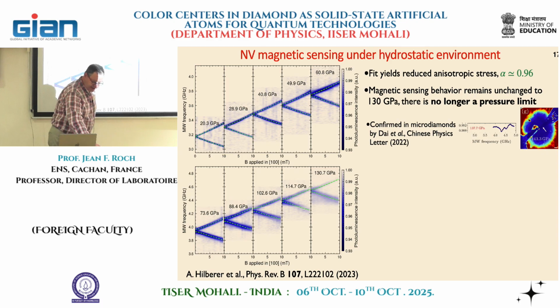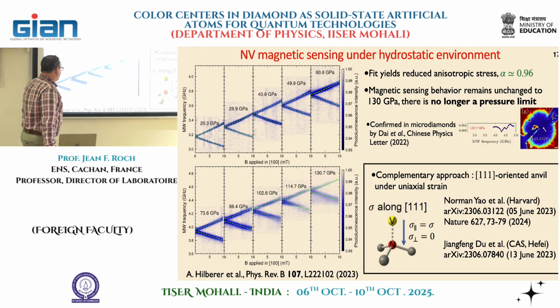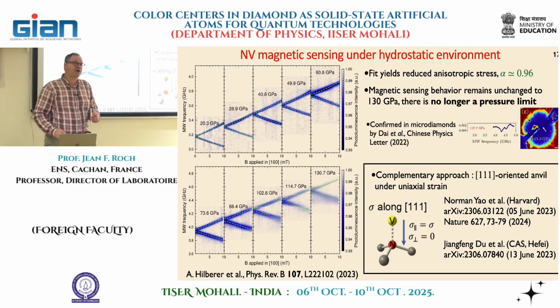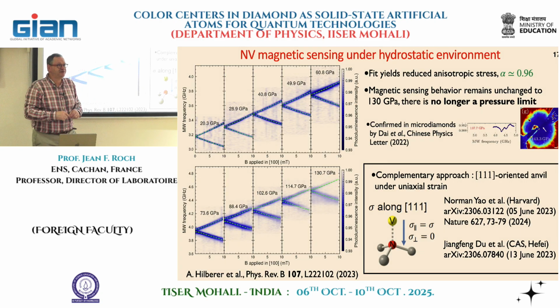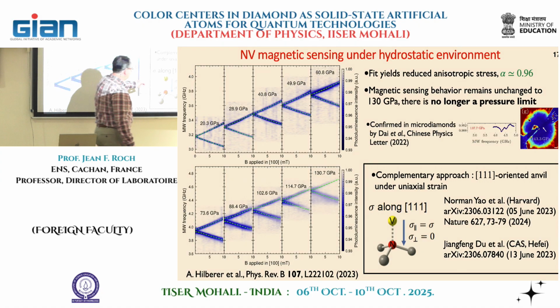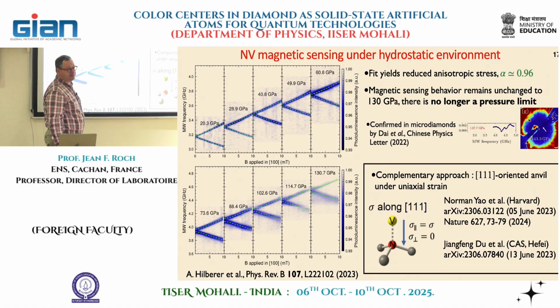And there was another approach that was complementary to ours, done by Norman Yao and also people in China, that now use (111) NV layers. In those (111) NV layers, you have one NV family in which you apply the pressure exactly on their axis. So for that family, it's really great because everything is perfect. You keep their symmetry by construction. So it's again another proof that it's indeed the C3v symmetry that matters in everything. And Norman has applied that in a very nice experiment which shows some kind of first evidence that superconductivity can be observed in superhydrides using the NV technique.